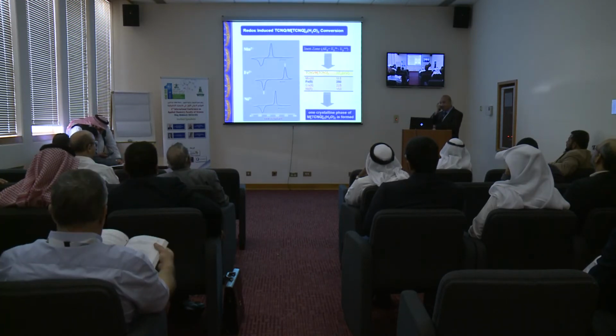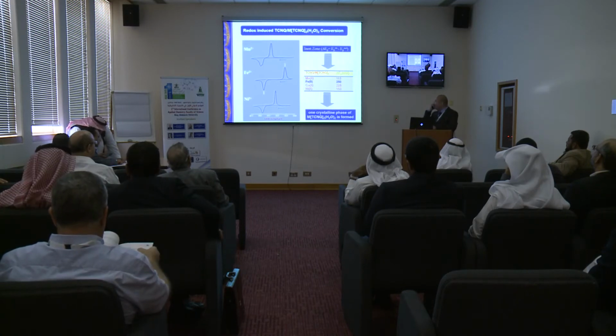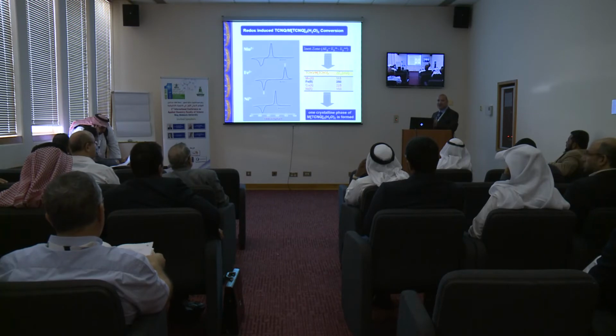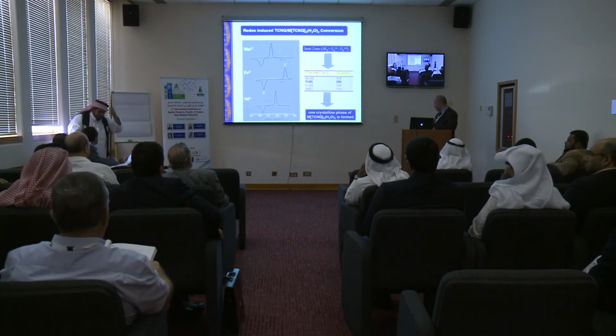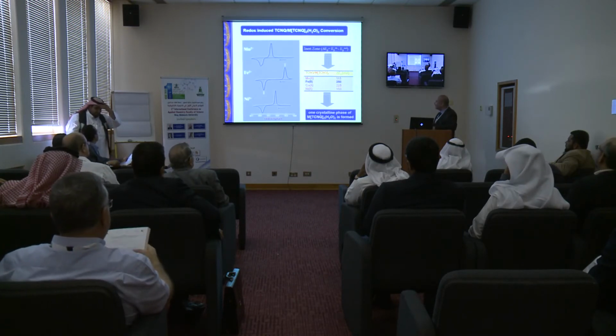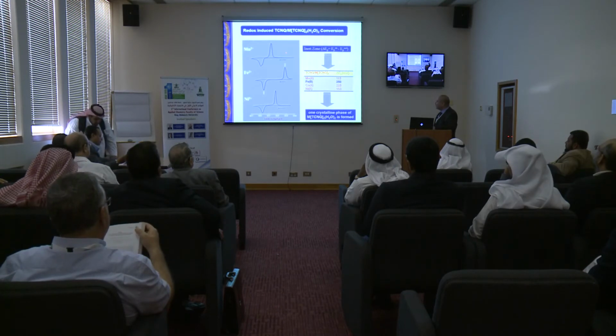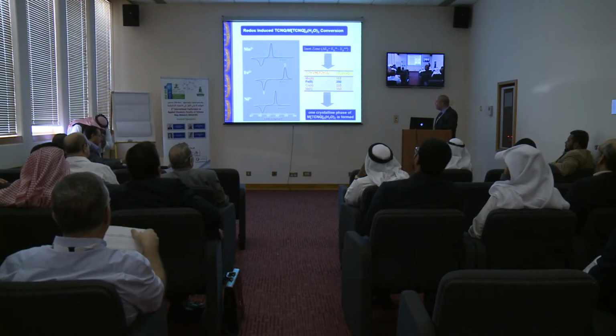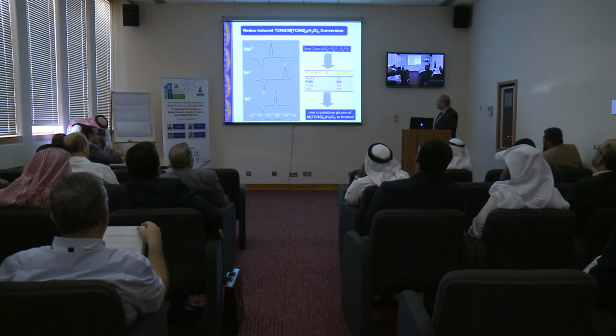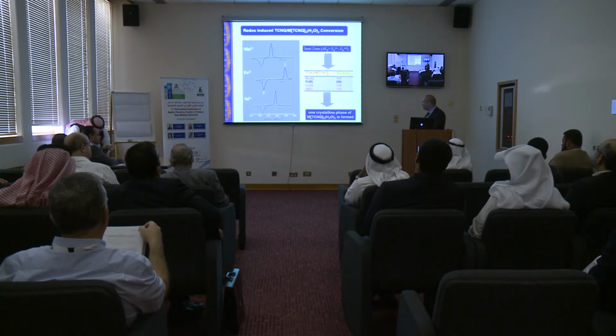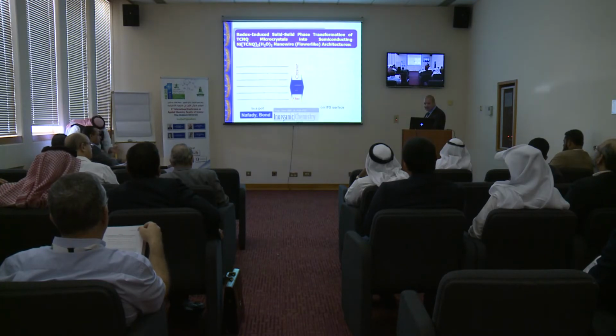A curiosity-driven phenomenon for any chemist: he would say, what would happen if you change the nature of the metal? So what we did here is we go for manganese, iron, and nickel. You can see the voltammetry is very much the same. However, we have different values for the delta EB. And this is a kinetic parameter, which means that the precipitation or the formation of these materials is metal dependent.